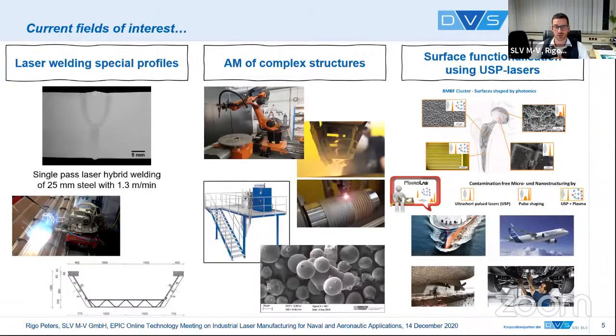First one is the laser welding of special profiles. On the left side here, we see a single pass laser hybrid welded profile with a thickness of 25 millimeters EH36, as we have seen in the last presentation. Here the welding speed, for example, was 1.3 meters per minute, which is quite high at this high thickness. For example, if you weld 5 to 8 millimeters, which is common in cruise liner production.